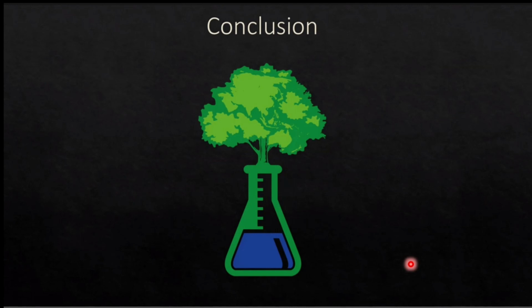So if you allow the orange or the red polymorphs of the copper iodide pyrazine MOFs to dry out, not necessarily heating, but let's say you expose it to air, and you allowed whatever water was going to naturally come off at room temperature, do they change back to yellow, or are those two polymorphs at least relatively stable enough to do that? Well, that's a very interesting question. So there's a bit of uncertainty there.